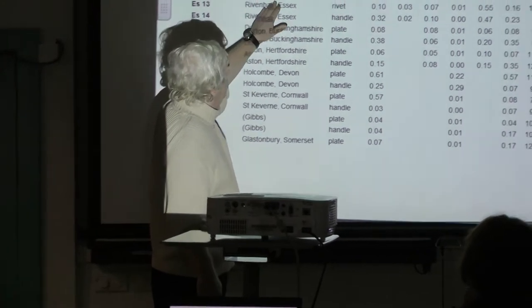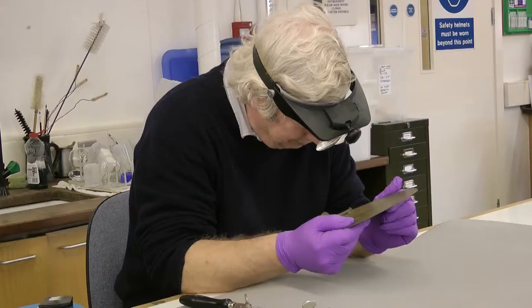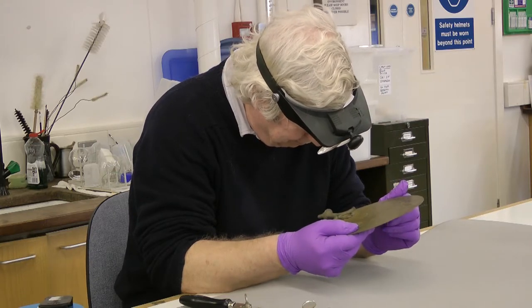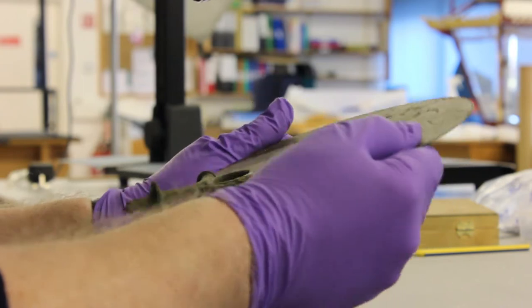Much of the past 40 years I've been researching the applications of metallurgy, particularly physical metallurgy, in archaeology. Everything that has happened to that metal since the bronze left the crucible leaves traces that you can identify with various sorts of microscopy and interpret. You can do a compositional analysis which can help you understand where the component parts of the alloy came from, and also help you interpret the structure — how it was cast, how it was forged. You can find out how it was finished, look at the corrosion and see what happened to it in the ground, and also see what the conservators and restorers have done to it since it came out of the ground.